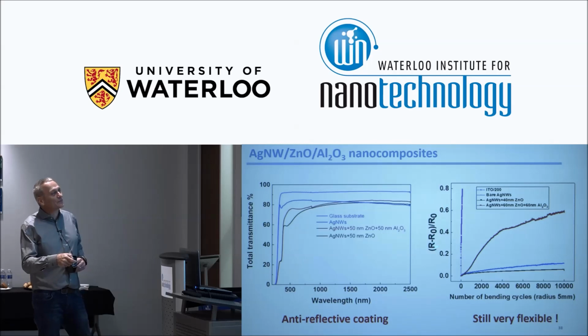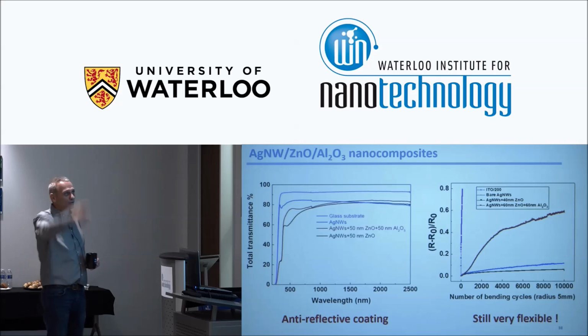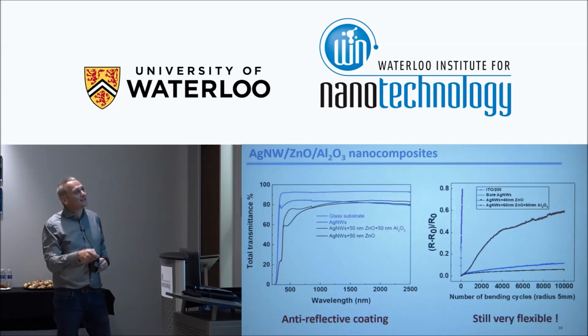This is minus initial resistance divided by the initial resistance. This is number of bending cycles. We reduced to 5 millimeters. We divided this data by 200 to be able to put the data of ITO. So this point should normally be 200 times above, so nearly in the sky. So for ITO, that's a catastrophe.